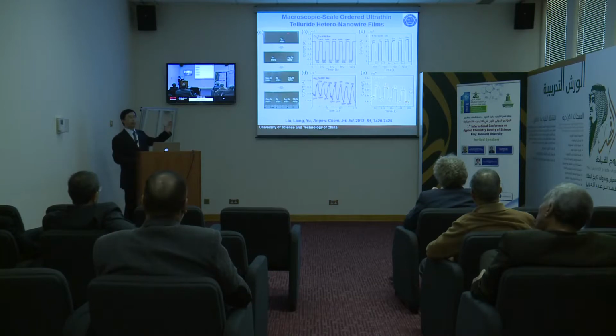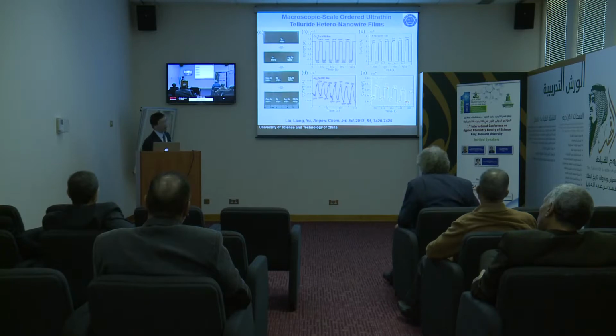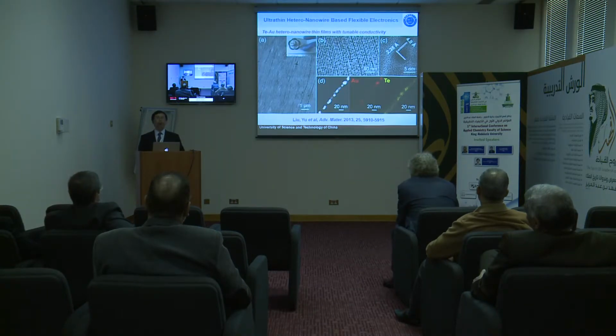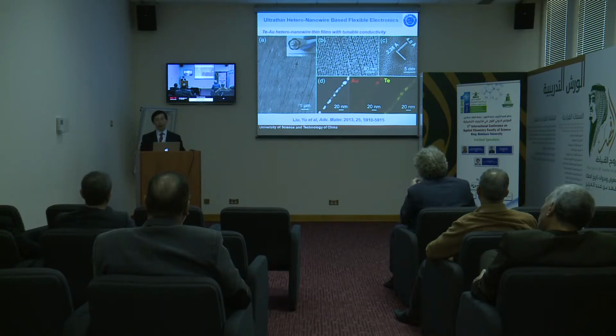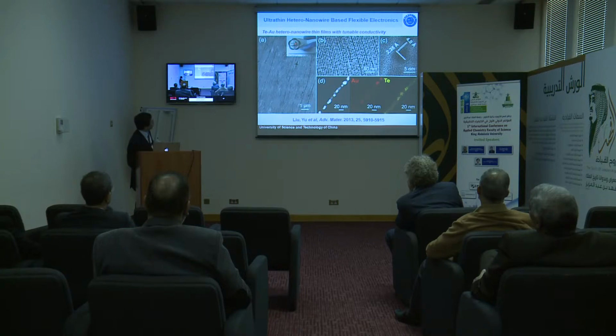And again, you can use these highly reactive tellurium nanowires as a substrate. You can react them partially with a different system. You can chemically transform them into different hetero-nanowire thin films, so that you can further engineer their photoconductivity in the future. And also, how can we use this nanowire to make a solid surface conductive? This is really difficult, but we can do it this way. We coat the surface.